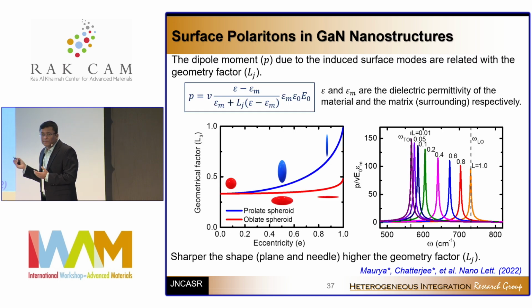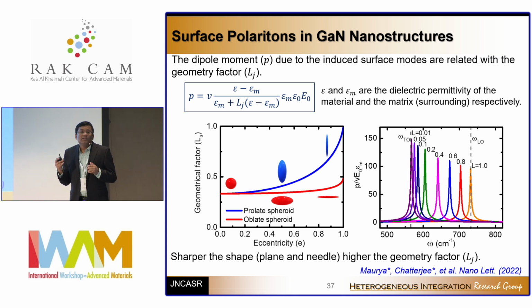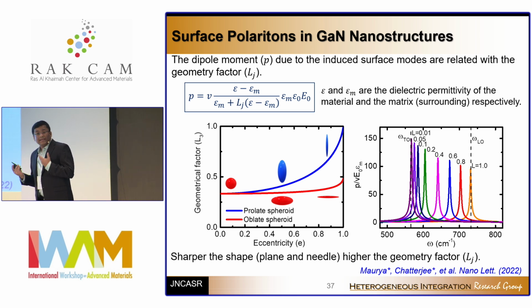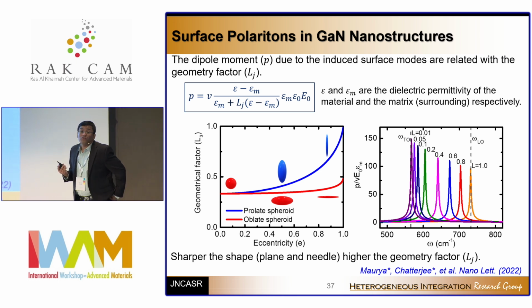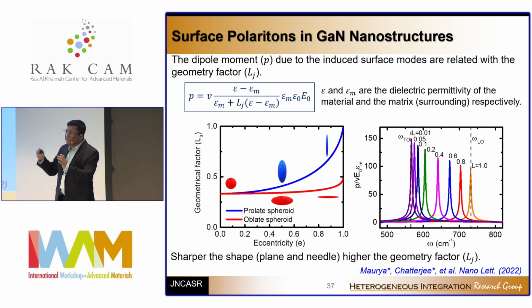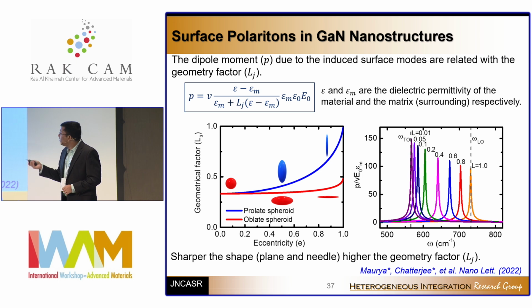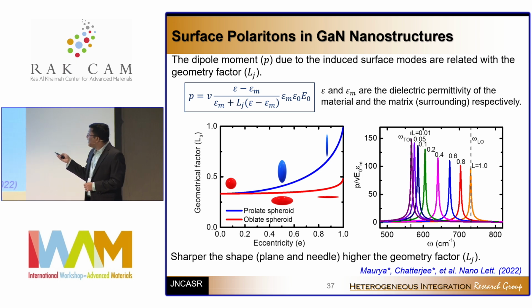I'll not go to the mathematics behind it, but physically what happens is that in these nanostructures, you have very large surface to volume ratio. If you have a large surface to volume ratio, that pretty much means that you have a large surface phonon excitation going on also. And light, just like it couples with other types of phonon modes, can also couple with the surface phonon modes. When it couples with the surface phonon mode, and depending on certain geometry, certain depolarization factor, and so forth, you can excite these absorption resonances close to the LO phonon frequency towards the TO phonon frequency.